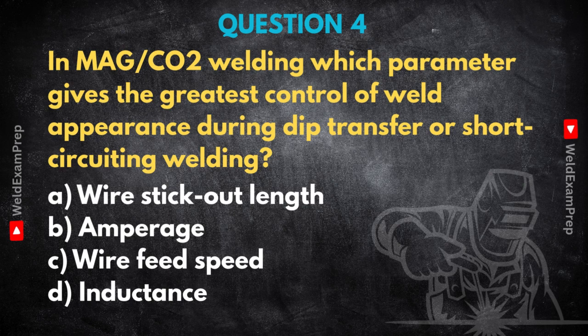Okay, this is specific to MAG using dip transfer or short-circuiting. What gives the best control over how the weld actually looks? The key parameter here is D, inductance. This one's interesting because it's often a bit misunderstood, but it's so critical for MAG, especially in dip transfer. So inductance basically controls the rate of current rise during that short circuit. When the wire dips into the pool, it shorts out. The current then ramps up really fast to burn the wire back. Inductance controls how fast that ramp up is.